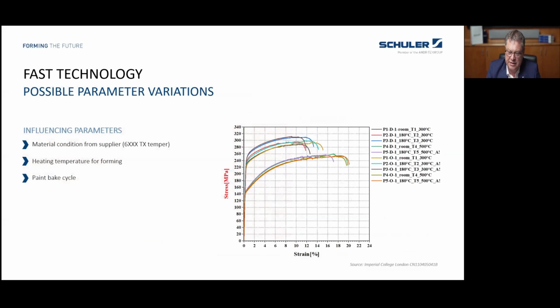So here you can see some of the measuring results. This was the result of the measuring of the tensile strengths and the yield strengths. And you can see that we did it with different paint bake cycles and also different preconditions of the material. But you can see finally, if you get the right setup, you can reach again the 310 here, in this case, the 310 Newton per square millimeter, which was more or less the material property of the ingoing material.